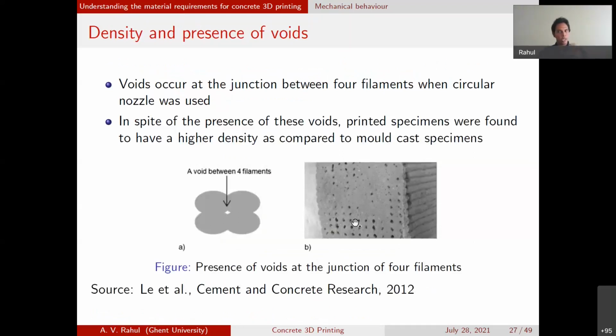Sometimes you also get problems with using certain types of nozzles. For example, if you use a circular nozzle, a small porous region can exist at the center, as you see here. This porous region can contribute to a lower compression and even tensile strength.